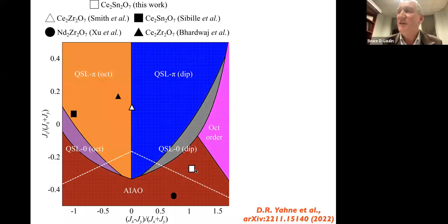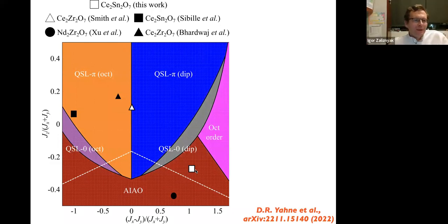However, there's another parameter in the Hamiltonian which I haven't told you about, which is related to the effect of the magnetic field, and it's a parameter theta. At any rate, if theta equals 0, you don't expect to see spin waves, but you can see spin waves if theta is non-zero. Something that I didn't mention for simplicity is that it's also consistent with our analysis that this theta factor is close to 0. I mean, maybe I'm missing something.